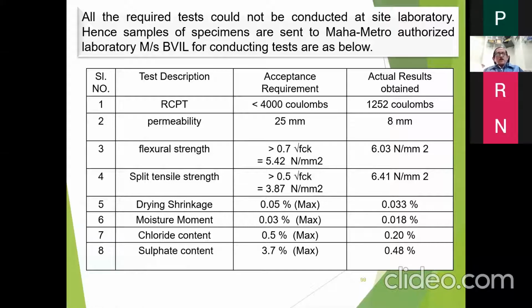Then all other tests such as rapid chloride penetration test, permeability test, flexure testing, split tensile test, drying shrinkage, moisture movement, chloride content and sulfate content were also done. The actual results were done in the Bureau Veritas India Limited laboratory. And we got a very good value of 1252 coulombs in RCPT, which is in the low category.